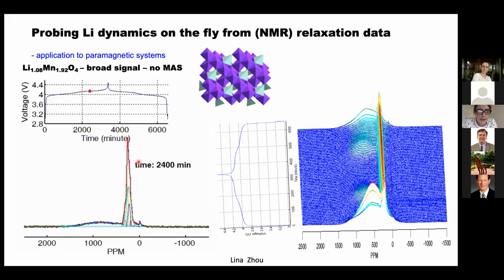These are now paramagnetic, and so the lithium interacts with the manganese ions and basically gives you broad lines. And we normally use this technique, magic angle spinning, to get rid of it, but in a static battery for in situ, we can't do that. So you get these broad features. This is lithium metal. Again, we're running the lithium manganese oxide in a half cell. I'll talk about the lithium metal signal a bit more.